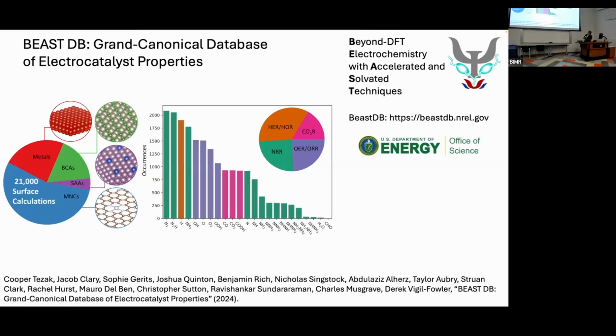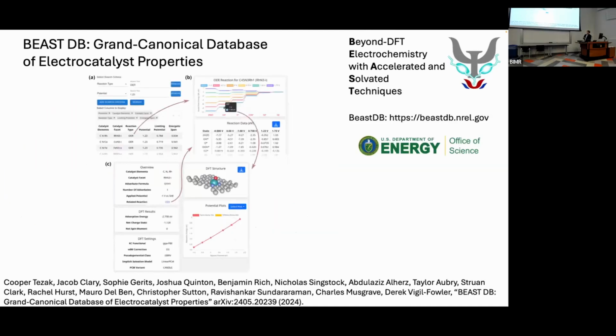If you're interested in different catalytic reactions, we have produced a new database called BeastDB. The name Beast comes from beyond DFT for electrochemistry. And it's beyond DFT, so we use grand canonical DFT for these calculations. We also vary the bias voltage in order to simulate realistic cases that you encounter in electrochemistry. You can access this database here. At this link, there's also a portal that you could access, and you can download the structures themselves, you can visualize them, and you can calculate as a function of the applied potential what the adsorption energy is, for example, because we've done the grand canonical DFT calculations here.